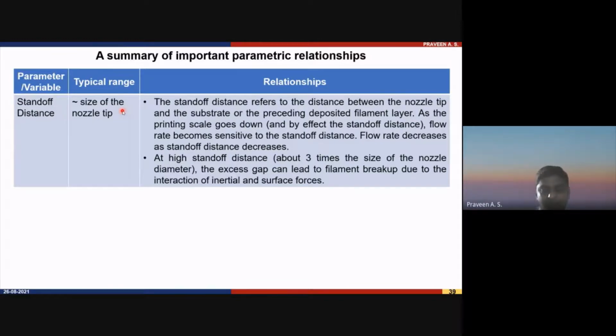If one line is already printed and you are printing another line on top of that, and the stand-off distance is the same as the printed line, what happens is the nozzle will go into that printed layer and it will drag that line. So you won't get that extra dimension, and your printed part will collapse. And if the stand-off distance is more than 3 times, there is no proper deposition. If you are making any spanning structures, you cannot ensure proper deposition of the slurry on the printed line. So we have to optimize.